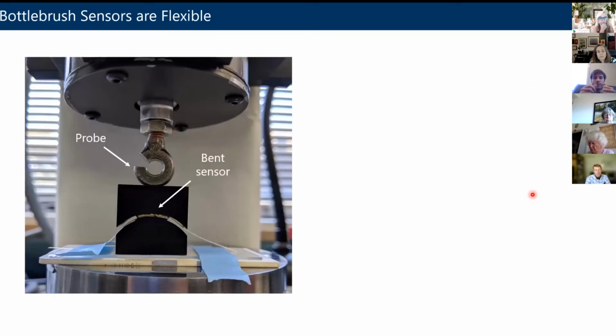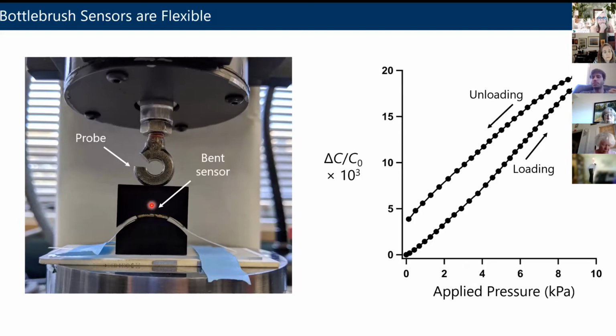Because it's with flexible electrodes, you can physically bend the sensor. You can see here the sensor's been bent. It's taped onto the table. We use this probe that's a hook for no reason other than that's what was available on the tensile tester at the time. So don't worry that it's a hook. We just smash that hook into the sample. And again, when it's bent, you still see a signal or a change in capacitance as a function of pretty low applied pressures. So these are actually nice pressure sensors.